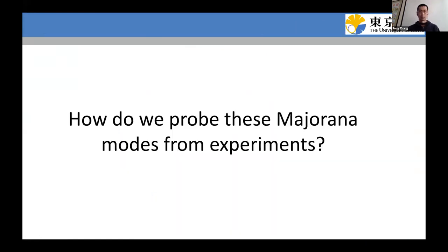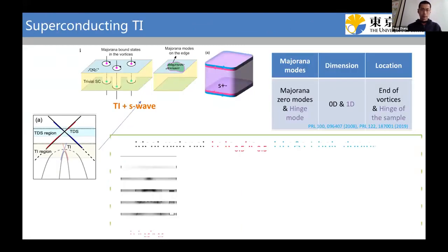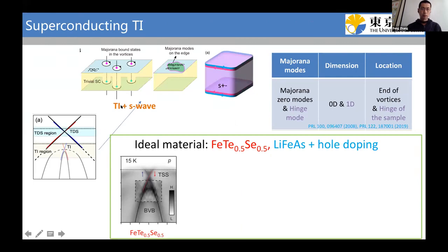How do we probe these Majorana modes from experiments? For this topological insulator plus S-wave case, the ideal material would be iron, tellurium, selenium, since we see from the band structure that the Fermi level is located very close to the surface Dirac point, which is a very good scenario for the Fu-Kane model.